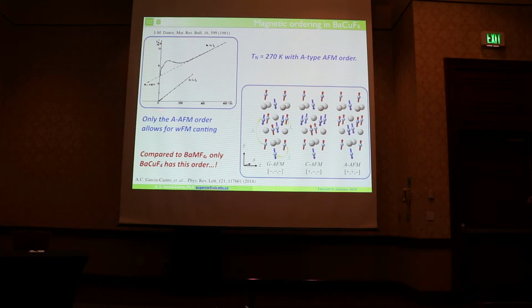So we tried to look first at the literature, and this is a really nice paper. I have to train my French. It's in French. They synthesized this crystal in the 80s, and measured the inverse susceptibility as a function of temperature, and observed that the Néel transition temperature is really, really high, which is very interesting for fluorides, which usually have a really low temperature, and it has what we call A-type antiferromagnetic ordering. Compared to the other family of materials, barium copper F4 is the only one that has this ordering.